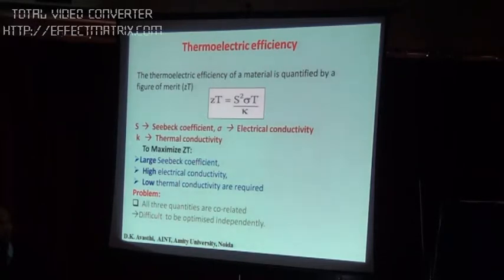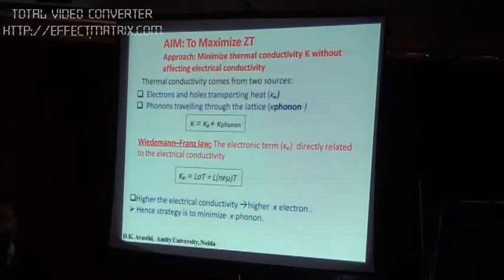So the strategy is this: the two are connected by this formula. Electrical conductivity and thermal conductivity are connected by this formula, and it is independent of K phonon. So you reduce K phonon, not Ke. If you reduce K phonon, then the electrical conductivity is not affected. You decouple it, and this is the strategy we used to improve upon the ZT.